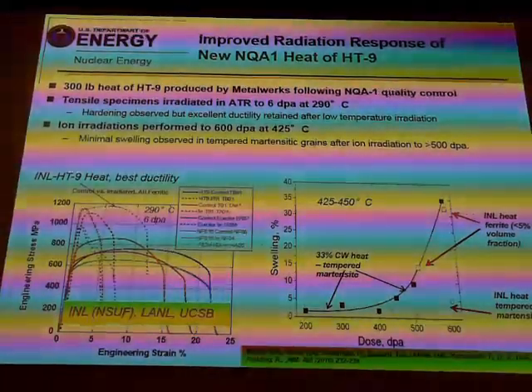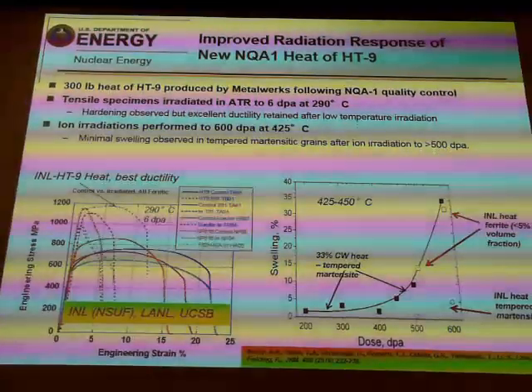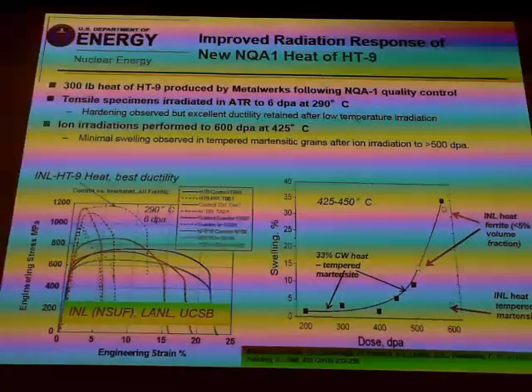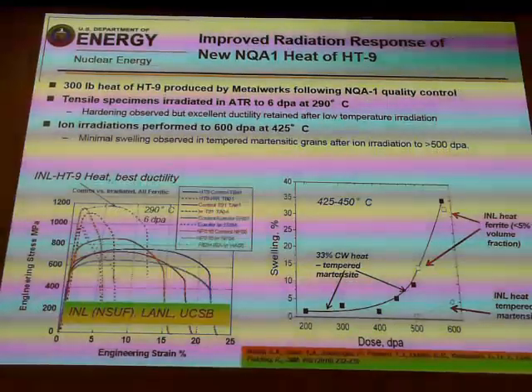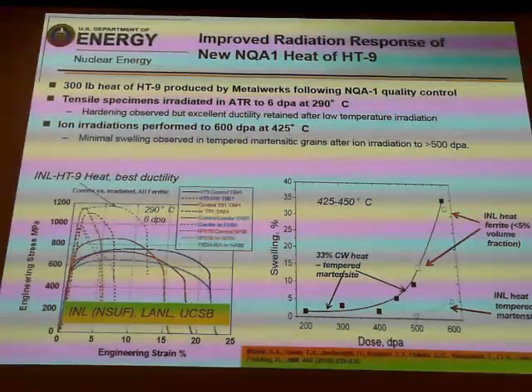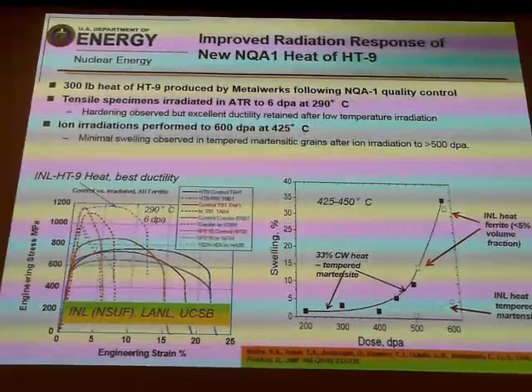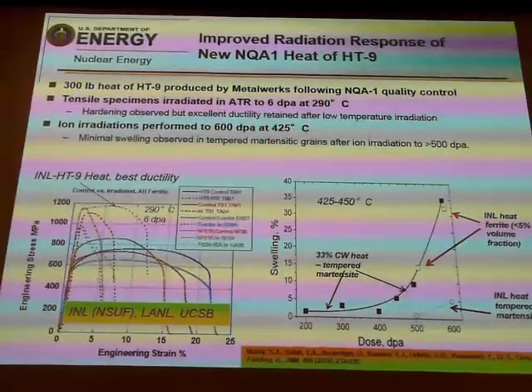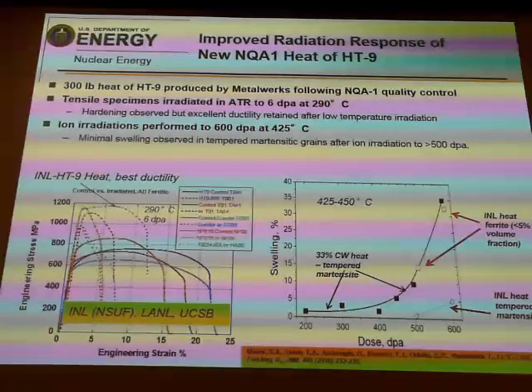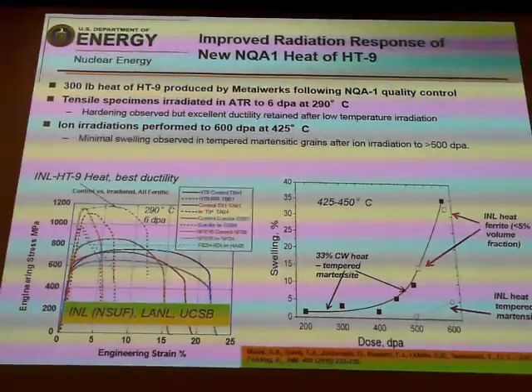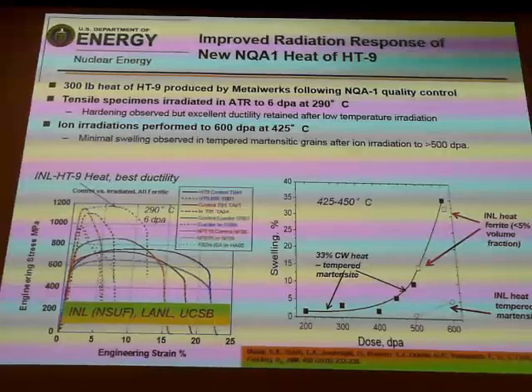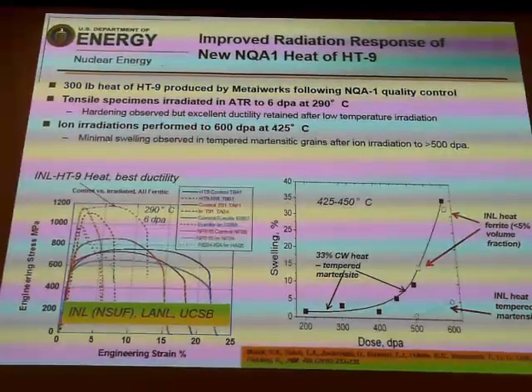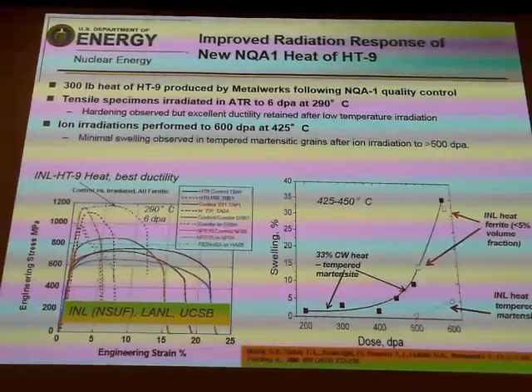And all these other materials, T91, Grade 92, NF616, and F82H, were all irradiated at the same time. They all show a drop in uniform elongation to about 1%, as you can see in all these curves right here. So something was better about that material that we've been looking at. We also did some ion irradiations to high doses.